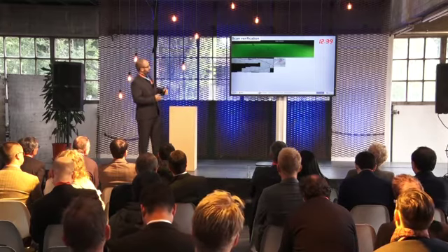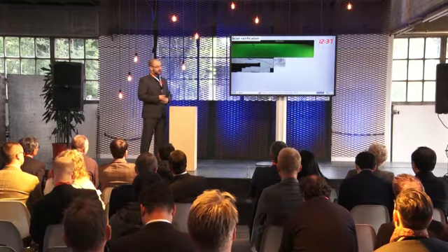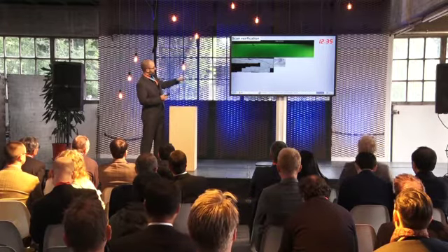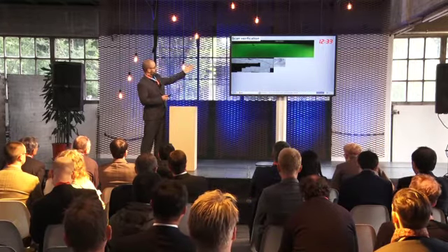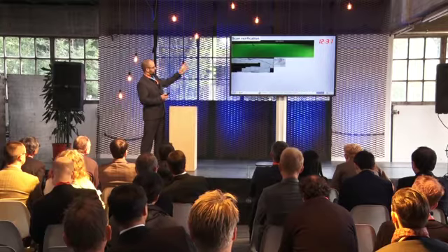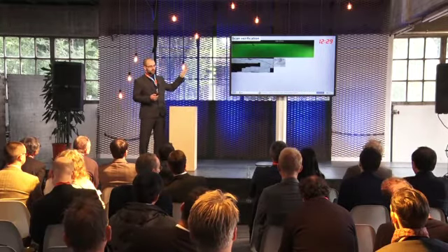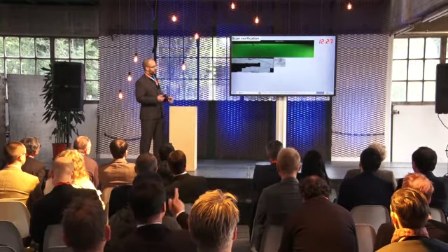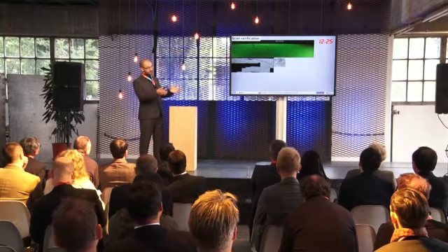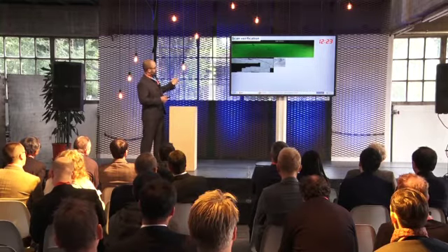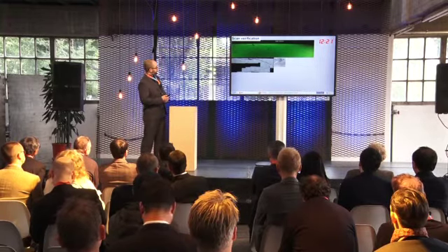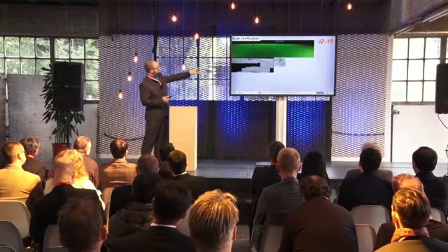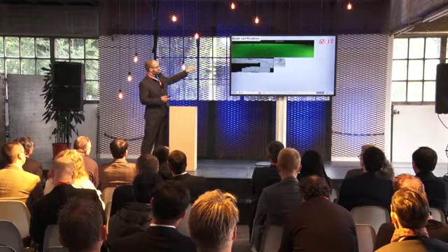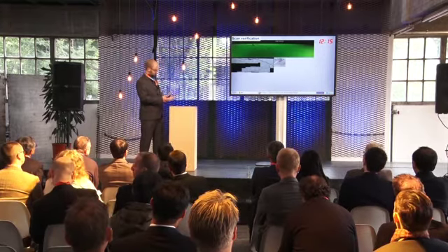At the top here, you have a false color image of one of the scans. As you can see from the unetched micrograph below, it is very similar. It hasn't picked up on all the detail due to the low resolution, and that's to do with the very large sample size that I put in, because it was a full rail width. But generally what it was picking up on was real, and what you're seeing between the three pictures is that consistent hole which actually breaks the surface. So, looking good.